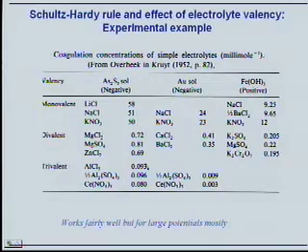Why do people, when they actually purify water, take water from a creek, and the first step in purification is dumping aluminum chloride inside the water? Now why is that done? Get out particulate matter, right. Any particulates, biological cells, whatever you have colloidal in water, is going to immediately aggregate and precipitate and so on. So this is the way to clear the water.